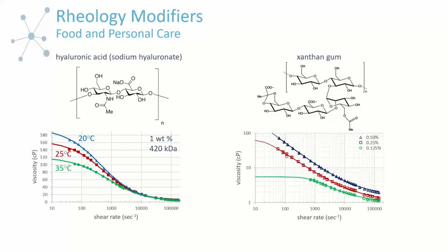And again, you can see as we adjust the concentration, and these are quite low concentrations because these are quite high molecular weight, and each individual monomeric unit is quite bulky, lending a lot of interesting rheological behavior. But we can see that we can adjust plateau values, range of shear thinning, and both low shear plateau and high shear plateau by adjusting the concentration.